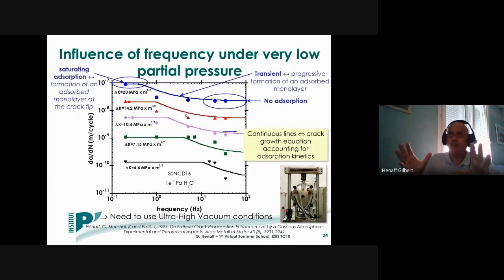On this slide, you have the same type of results here in the case of a high-strength low-alloy steel, but here the water vapor pressure is fixed to a very low value, 10 to the minus 3 pascals. And here we have some data obtained at different frequencies for fixed values of the delta K parameter. And you can see that for any delta K value, you have the same type of behavior with a high fatigue crack growth rate at low frequencies, then a transient regime, and the plateau here corresponding with higher frequencies. And this type of behavior was interpreted as follows.